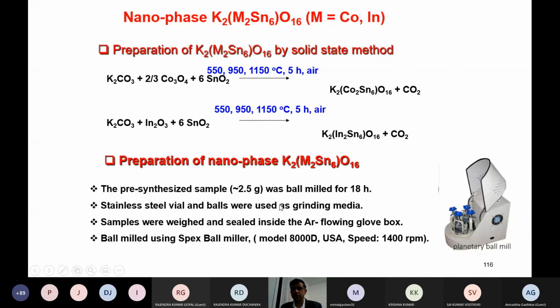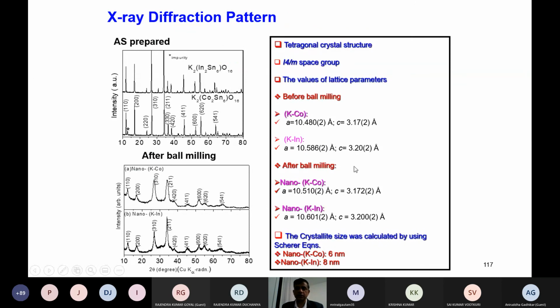Again, we can reduce the particle size by using the ball milling approach, and we can get nano-size materials. You can see that the bulk material has bigger particles, while the nano material shows broadened lines. These are the various ways, as a material researcher, that X-ray diffraction technique is sometimes very useful.